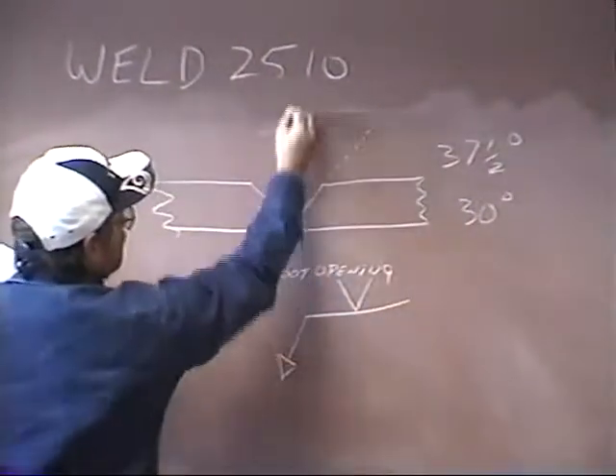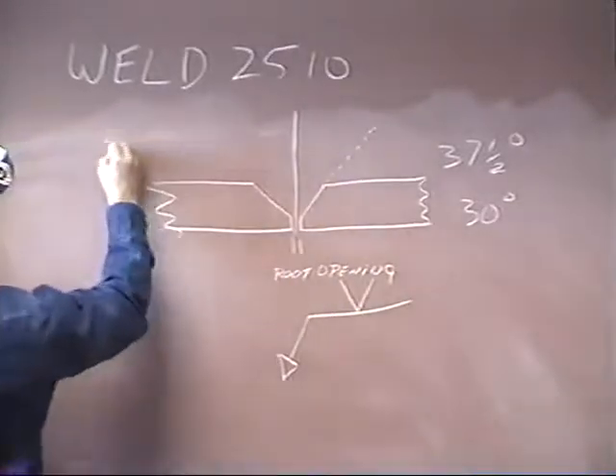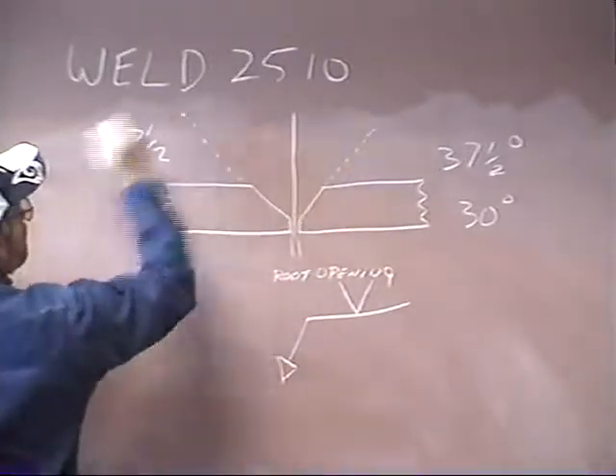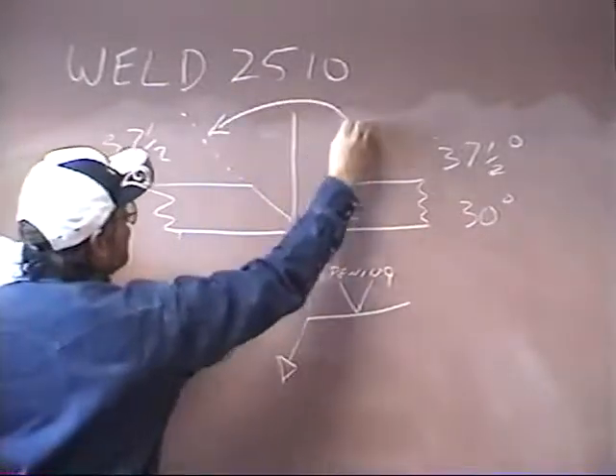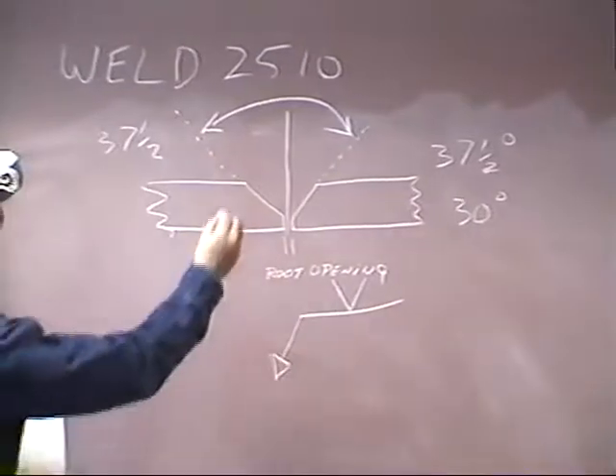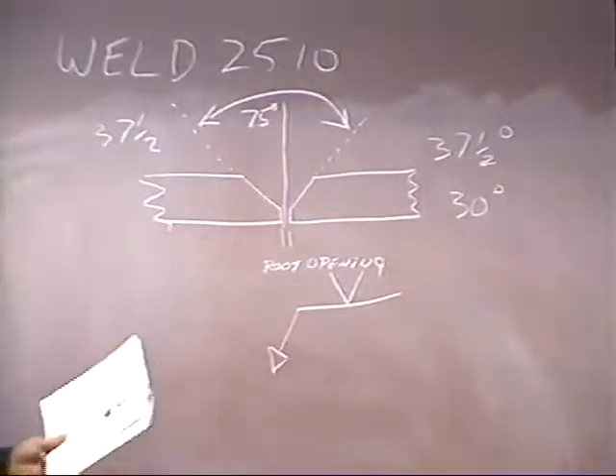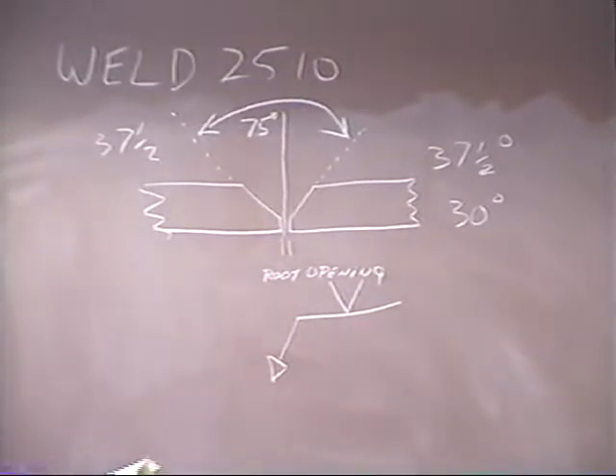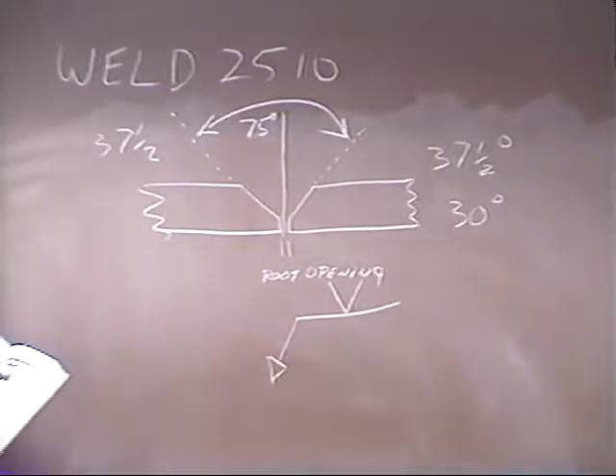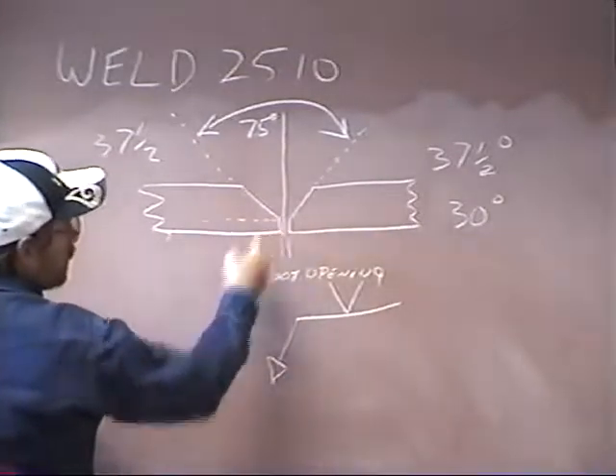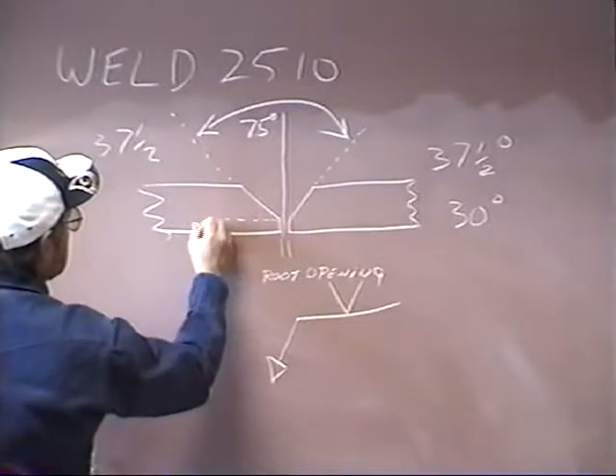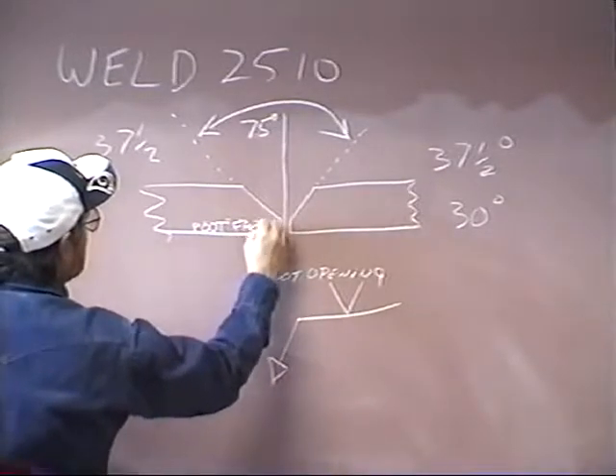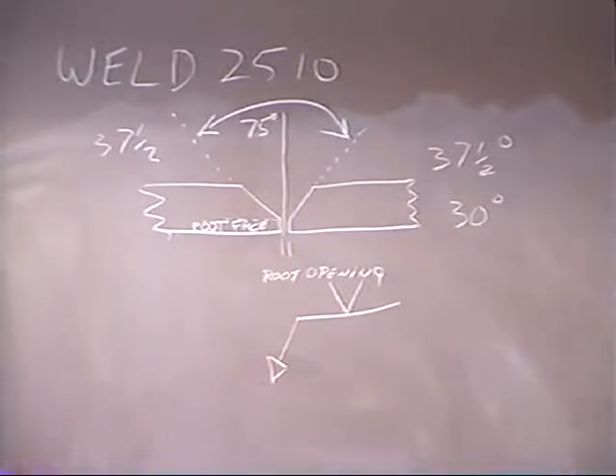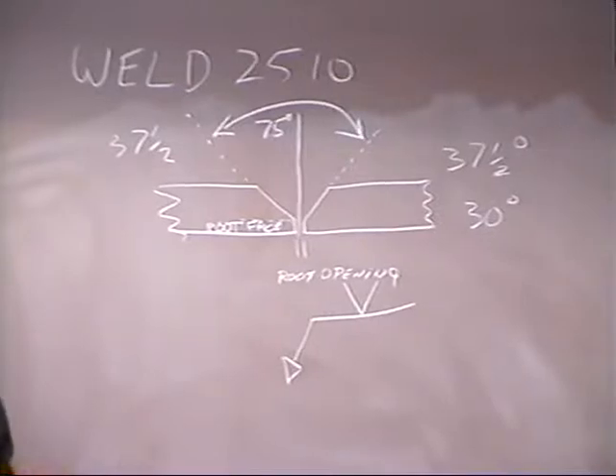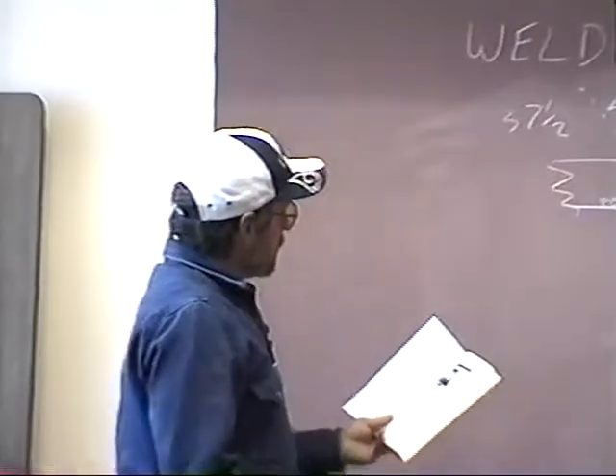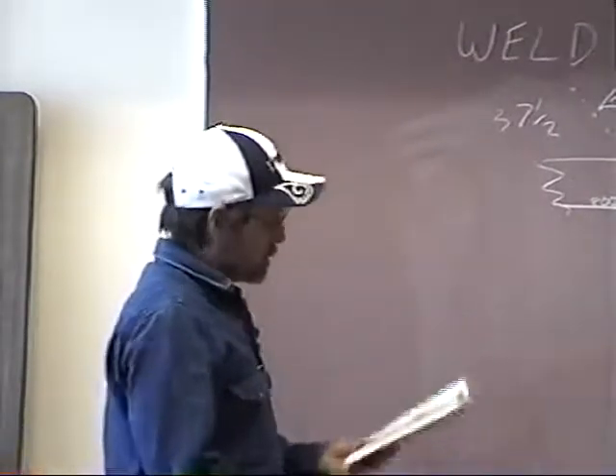So that's one bevel. Well, we got 2 bevels here. So we got 37.5 and 37.5 on each side. So the included angle, that is the 2 of them added together, is going to be 75 degrees. And that is called your included angle. You should memorize these. They will be on your test. Right here, what we call our land is properly called a root face. And that can be of varying sizes depending on the welding procedure specification and whether or not you're welding vertically up or vertically down. I believe that's all your book talks about on this one.